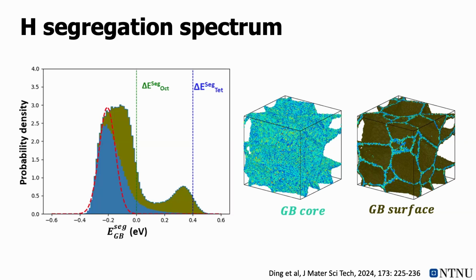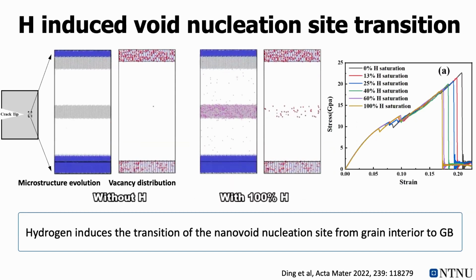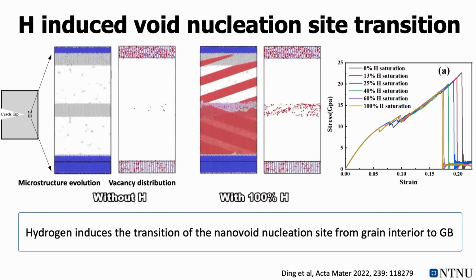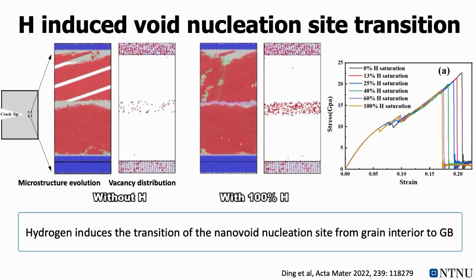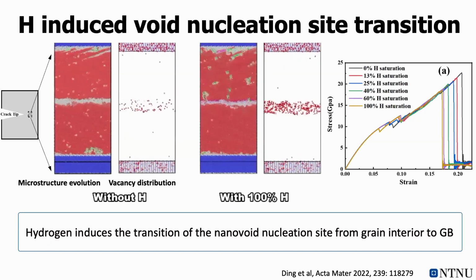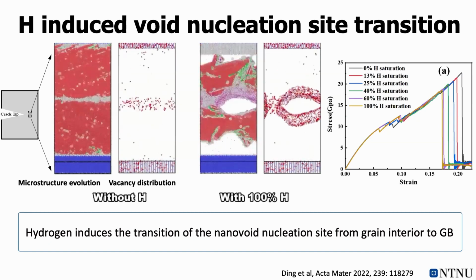If we further divide the grain boundary into the grain boundary core and the grain boundary surface, we can see that most of the lower energy part is the grain boundary core rather than the surface. That also confirms that hydrogen prefers to stay in the grain boundary, really inside the grain boundary. From this segregation energy spectrum, we can see the severe consequence we could have. We move from polycrystalline to bicrystal, so we can focus on hydrogen interaction with an individual grain boundary. And we simulate this very high stress field area.